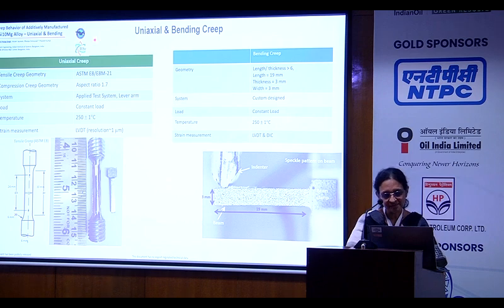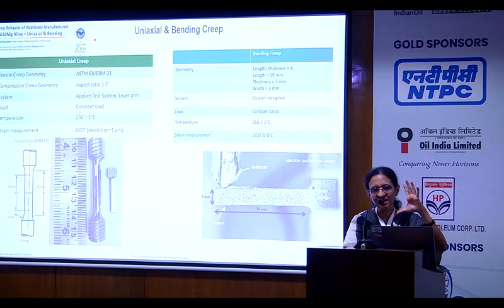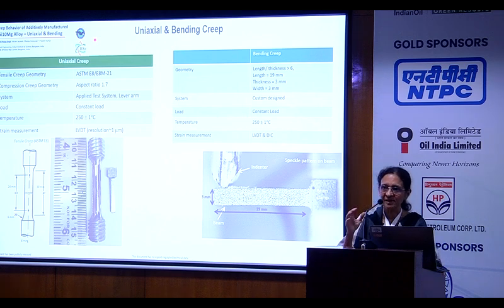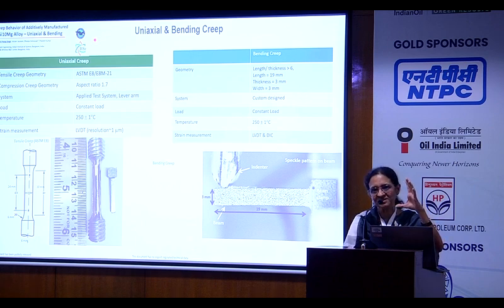So if you look at conventional ASTM, we have 100 millimeter, 4 inches, 2 inches, and so on. In contrast, we are developing an entire specimen which is no more than half an inch, and the whole thickness of it could be as low as 500 microns, 0.5 millimeters. Take test specimens out of it and prove that the mechanical properties, especially the strength and creep properties, in this particular example it's creep, we're also working on fatigue, of course, is equivalent to the standard ASTM large test specimens, and thereby accelerate.